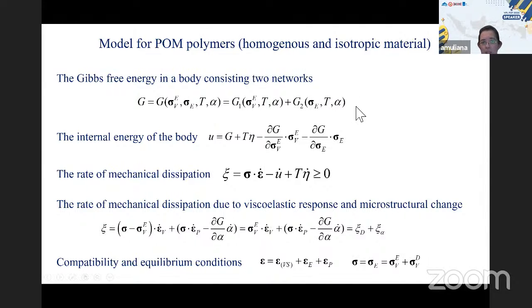As I mentioned earlier, the idea of microstructural changes and viscoelastic material is that there is energy dissipation. So here we quantify the rate of mechanical energy dissipation. All of this is derived from thermodynamic principles. I'm just going to show you the final breakdown here. We can quantify the rate of mechanical dissipation due to the delayed response, or viscoelastic effect, and the rate of mechanical dissipation due to the microstructural changes, right? Now, through linking the stress and strain, we satisfy the compatibility and equilibrium equations.